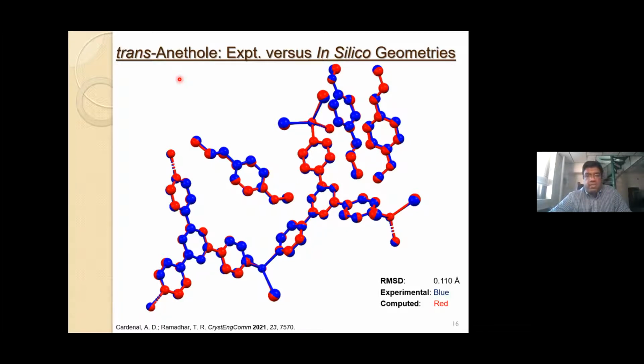And as you can see, the red structures are the computed structures, the blue structure is the experimental structure, and you can see that there's a relatively good agreement, or great agreement, between the experimental structure and the computed structure, and the actual error was low between them. So the RMSD was 0.110 angstroms, which indicates great agreement between the two. And it shows that we were able to use computational gas phase calculations to accurately reproduce the experimental structures that involve solvents. So it wasn't necessary to implicitly or explicitly deal with solvent in these sorts of calculations.